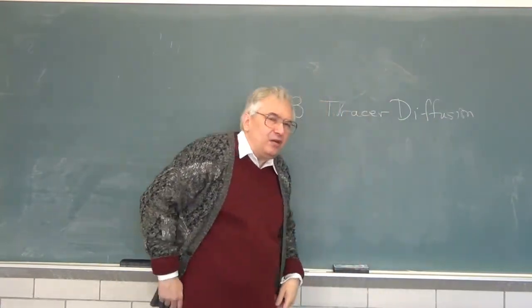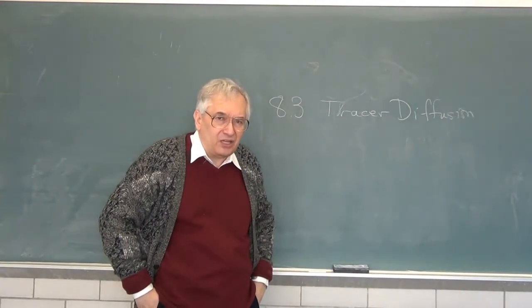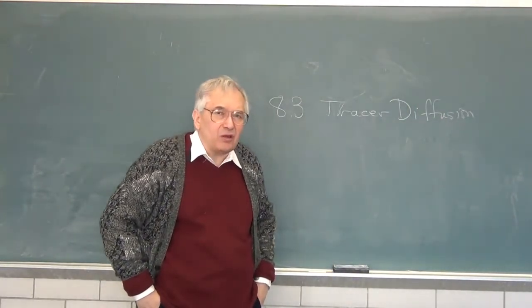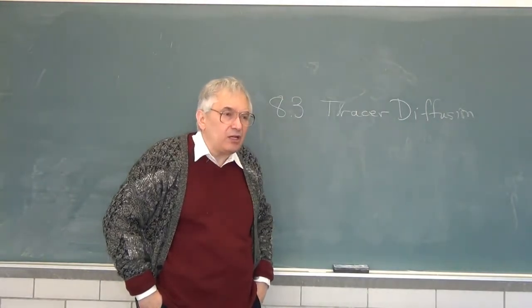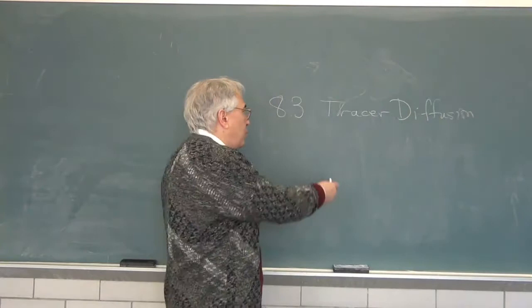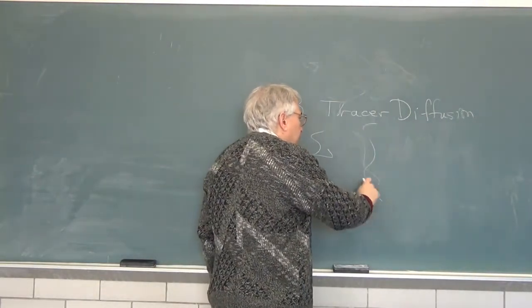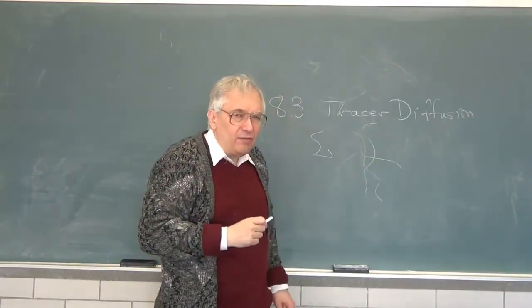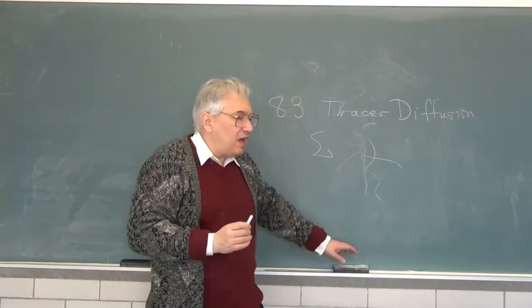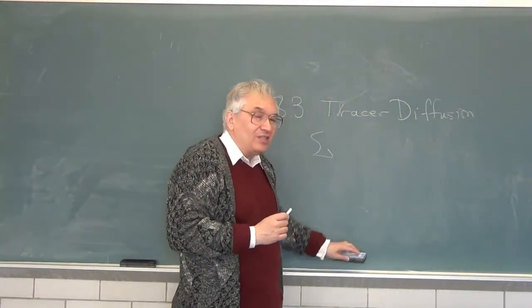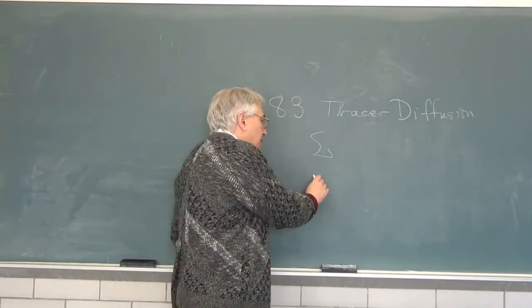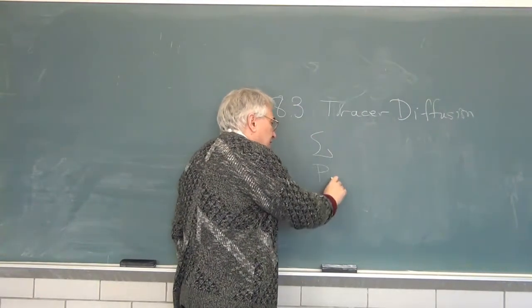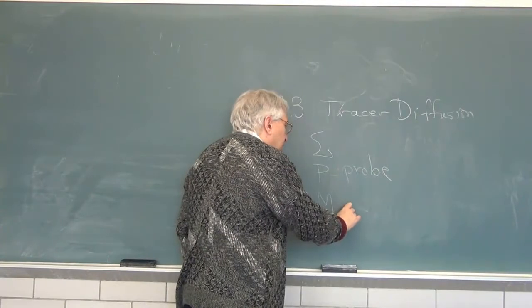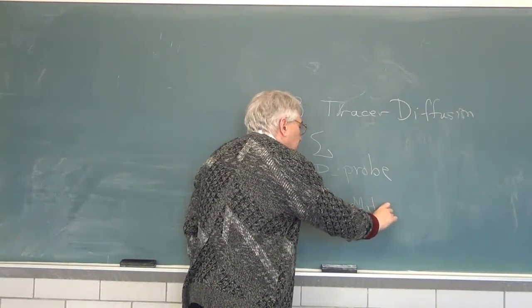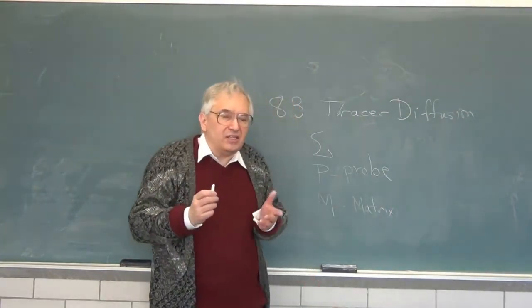which is an experiment we have seen before when we talked about dielectric relaxation, centrifugation, and electrophoresis, is that you have the probe particle, you have the polymer matrix, and if you have some way of identifying your probe particles and seeing them and making the matrix polymers invisible, you can separate out the dependence of D on the molecular weight of the probe and the dependence of D on the molecular weight of the matrix. And you can study these separately, or you can study these in tandem.